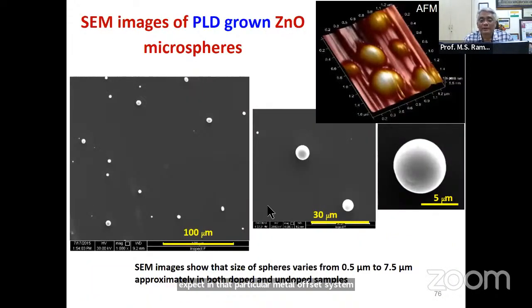So we grew films using PLD, an extraordinary technique. You can get extremely smooth layers, or nanorods, whiskers, and all that. By tuning the conditions, we could get these droplets. Normally you don't want droplets while growing thin films, but these droplets are useful if you pick them up and excite them with a laser source.